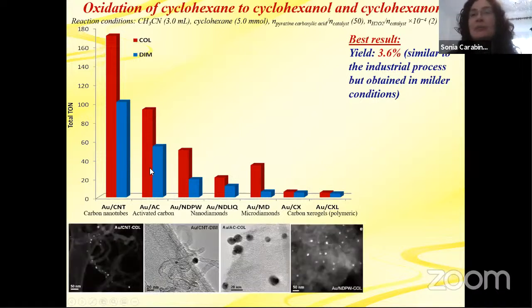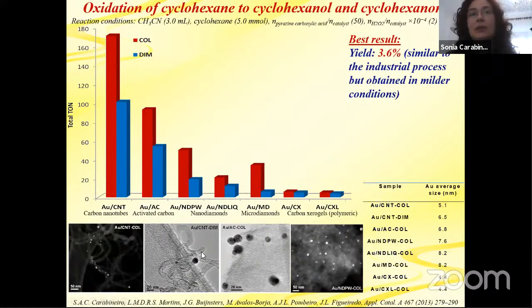So here we have some TEM images of these catalysts, the nanotubes, prepared by both methods. So this is the colloidal metal and the double impregnation method that I talked about before. So the colloidal metal was more effective in all catalysts. So better results were obtained. And if we look here at the gold sizes, we see that it was supposed that the best catalysts would be the xerogels, if only the size of gold nanoparticles would matter. But no, we see that carbon nanotubes are in fact the best, and the xerogels, although they have a very small nanoparticle size, they were not active at all.